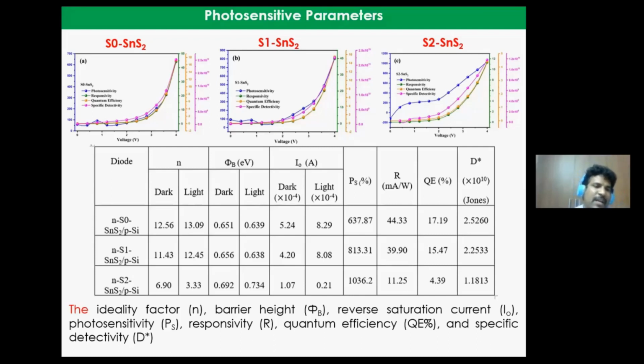S1, SnS2 shows a very poor ideality factor, and S2, SnS2 shows a very good ideality factor when compared to an ideal diode. The ideality factor of an ideal diode is equal to 1. But these two results, calculated for S1, SnS2 and S2, SnS2, show a huge difference. With this, we can predict that the layer formation with disc-shaped particles shows a huge difference from the flat particles.